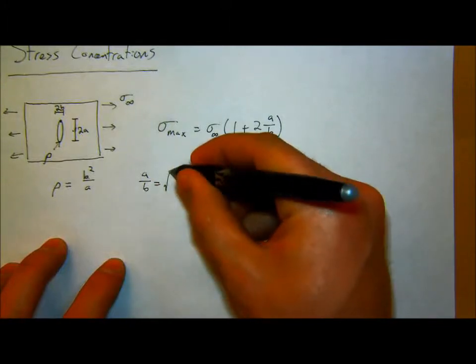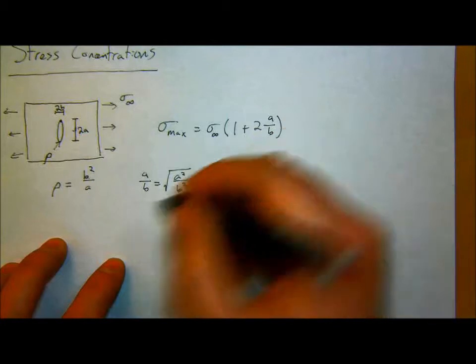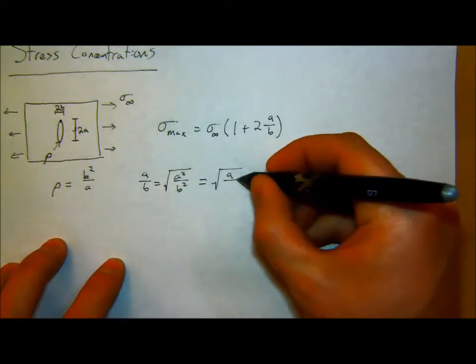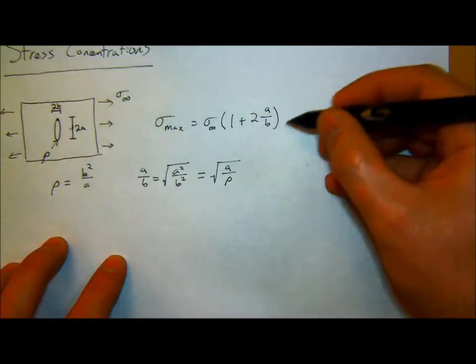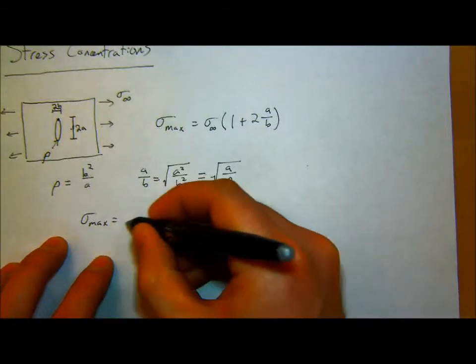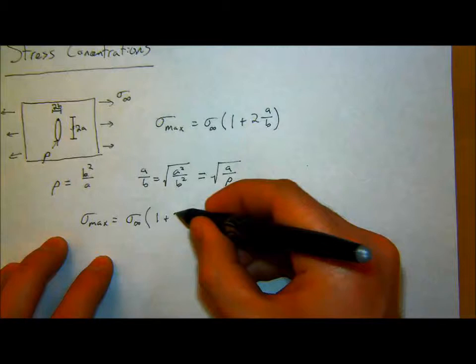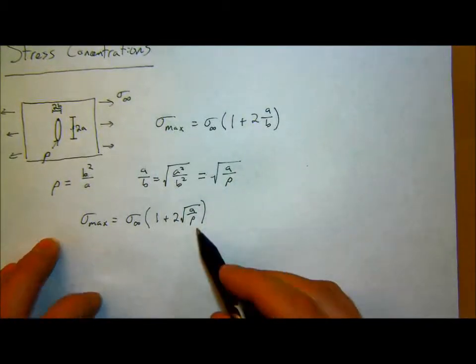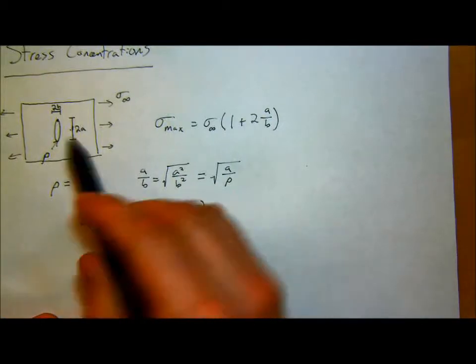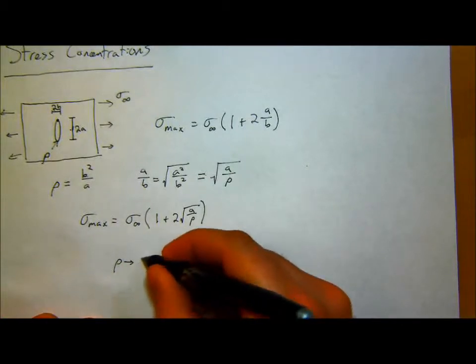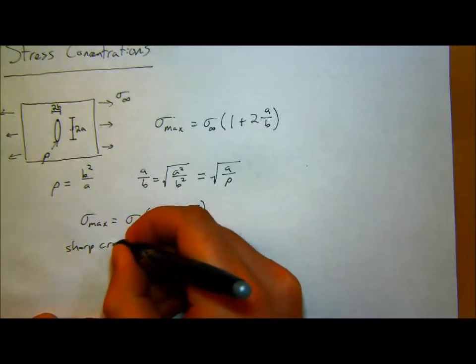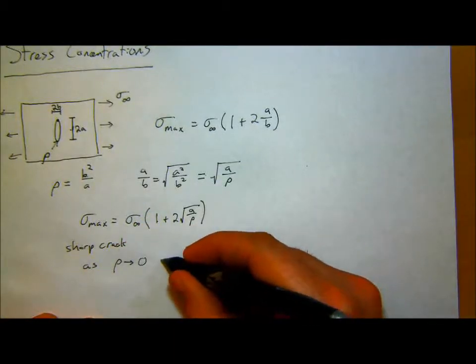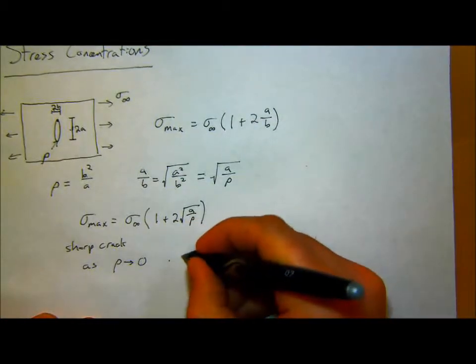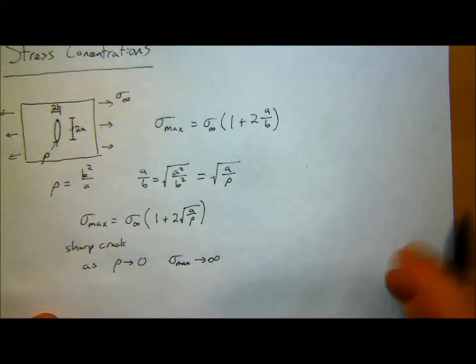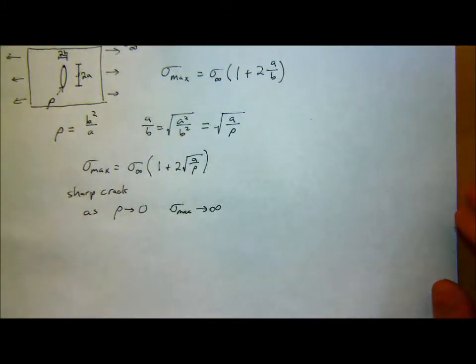So now I'm going to rewrite my sigma max in terms of rho. Sigma max is equal to sigma infinity times 1 plus 2 square root of A over rho. And now, as this crack becomes sharper and sharper, as rho goes to 0, a sharp crack, then stress max goes to infinity. Which isn't entirely practical. We know there can't be an infinite stress concentration at a thing, otherwise nothing would survive ever. The smallest tiny crack would just cause parts to catastrophically fail. But this is a useful way of thinking about it.